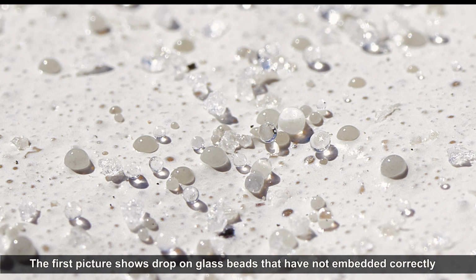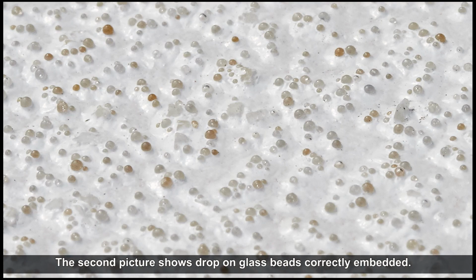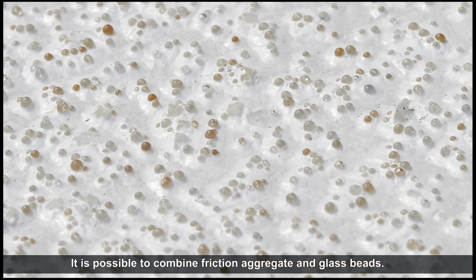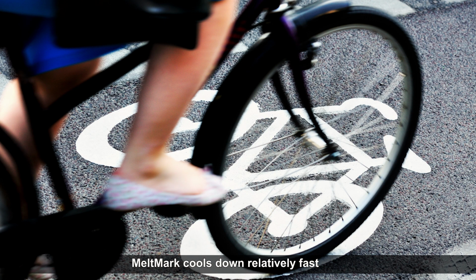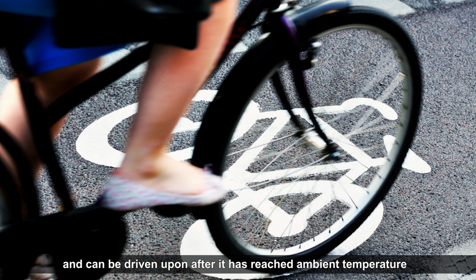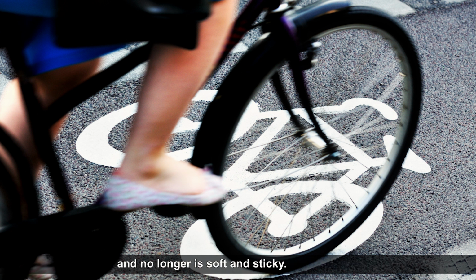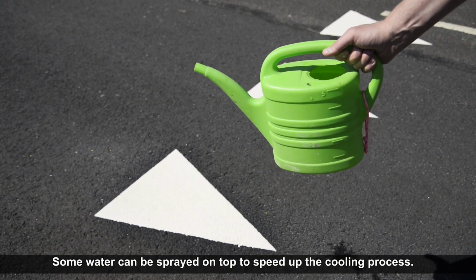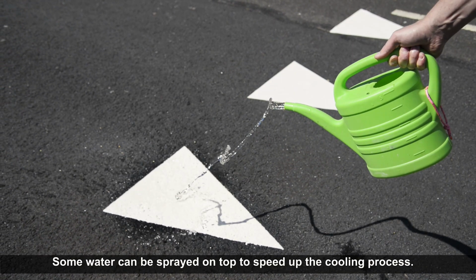The first picture shows drop-on glass beads that have not embedded correctly. The second picture shows drop-on glass beads correctly embedded. It is possible to combine friction aggregate and glass beads. MeltMark cools down relatively fast and can be driven upon after it has reached ambient temperature and no longer is soft and sticky. Some water can be sprayed on top to speed up the cooling process.